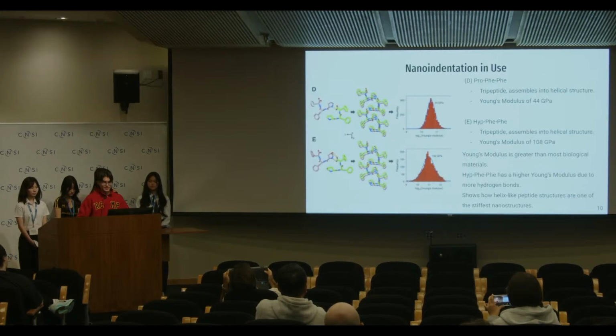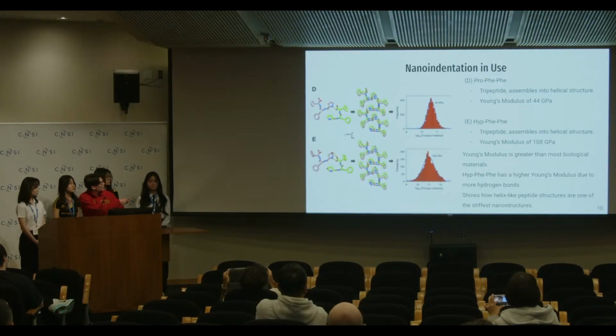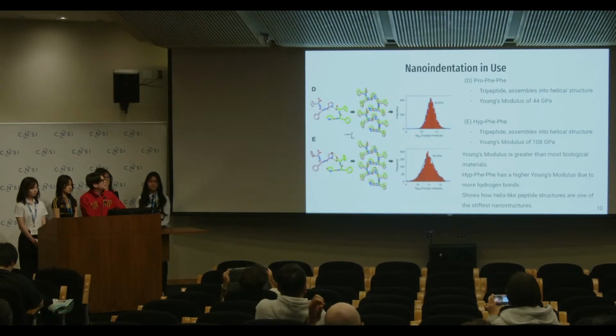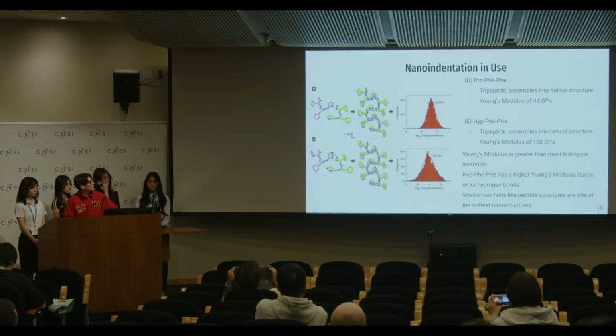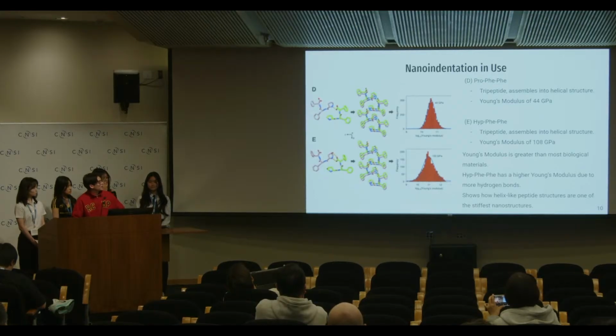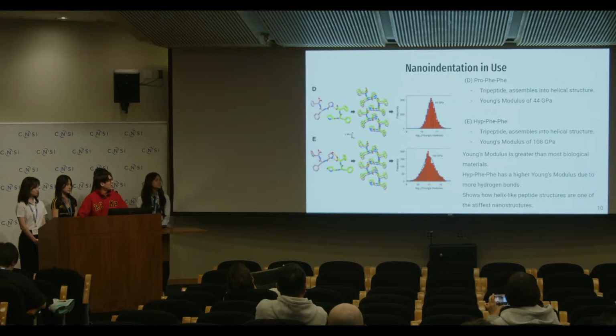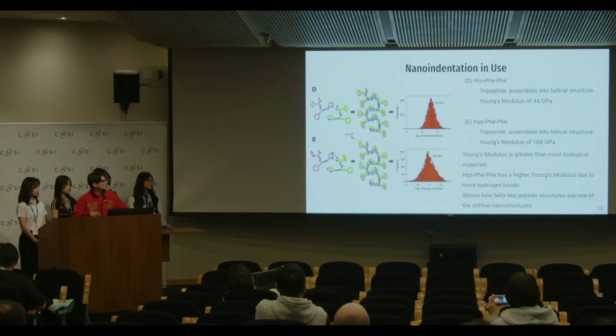And then nano-indentation in use. So this is also from Figure 9, as we saw earlier. The D here is the Pro-Phe-Phe molecule. And we use nano-indentation to measure the Young's modulus of it. So Pro-Phe-Phe is a tripeptide that assembles into a helical structure. And we measured a Young's modulus of 44 gigapascals, and this is a lot higher than average biological materials. So you can see how this helical structure gives it a lot of support and stiffness.